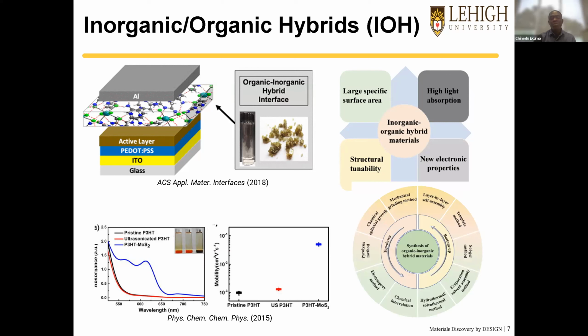Synthesis-wise, speaking with some of my experimental collaborators, they have said that these materials are generally very easy to synthesize, using various approaches from chemical epitaxy to pyrolysis to electrospray method, chemical intercalation, electrochemical intercalation, and the rest of them are some of the many routes that we can easily grow this hybrid structure. So, experimental design-wise, we have lots of ways to be able to grow them, because one issue with new material is that they are generally hard to make, limiting their potential applicability because we can't grow them at large scale. But in these organic and inorganic hybrids, they are generally easy to grow using well-established approaches.